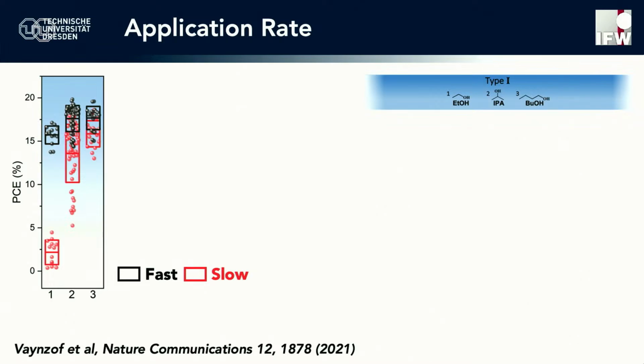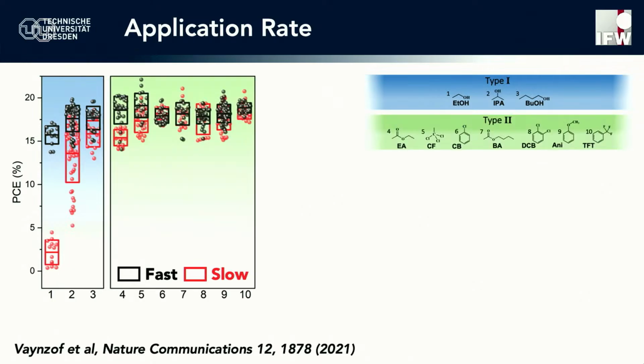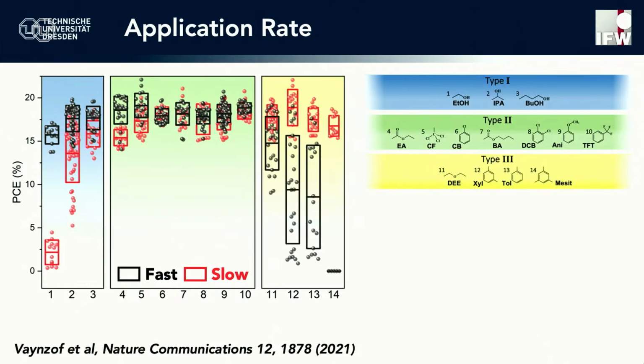In type 1 anti-solvents, if you deposit them quickly, you get very good devices. If you deposit them slowly, even though it's the same anti-solvent, you either don't get any performance or you get rather poor devices. Then there is a second category of anti-solvents where it doesn't seem to matter too much if you do it slowly or rapidly. And finally, there is a third category where you have to work slowly. If you deposit them slowly, everything works, you get high efficiencies. If you do it too fast, you have poor devices, or in the case of anti-solvent 14, that's mesitylene, no devices at all.